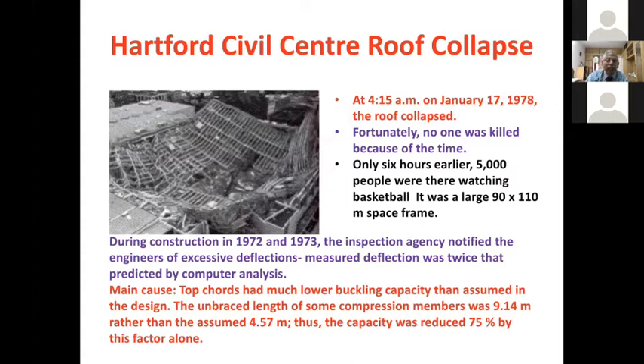Actually, during construction in 72 and 73, the inspection agency notified the engineers of excessive deflections. Measured deflections were twice that predicted by the computer analysis. So this failure shows that computer analysis itself is not sufficient. You got to be very careful to study the behavior of the structure before designing them.